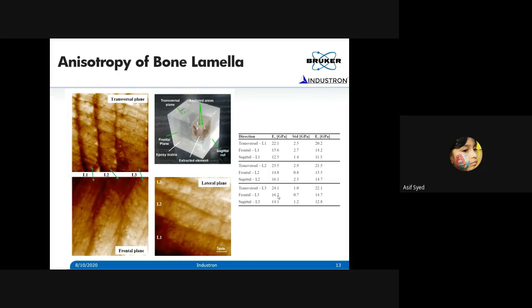So this gives you an idea of how we can use these tools to understand the mechanical response of this material. Bone is a very complicated structure, and without this kind of imaging technique where we can image the surface and choose a site where you want to do the indents, it's very, very difficult, because in an optical microscope, you won't even be able to see this structure and measure those properties. That is the uniqueness of this technology, where you can do scanning probe microscopy, get an image of the surface, and then select the site where you want to do the indent. That is the advantage of this technique.